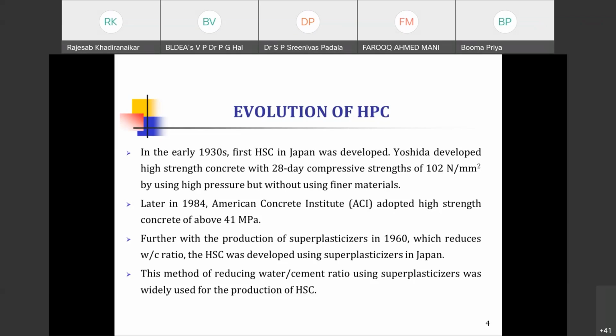But for in situ construction, going in for these kinds of techniques may not work. However, they were able to produce a high strength by applying high pressure. That was the earlier attempt, and later in 1984, the American Concrete Institute adopted high strength concrete as a concrete with a strength more than 40 or 41 MPa.